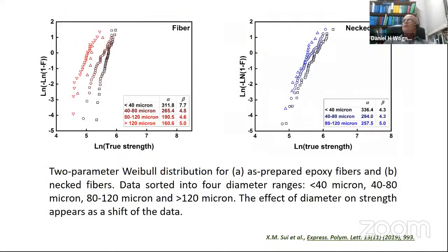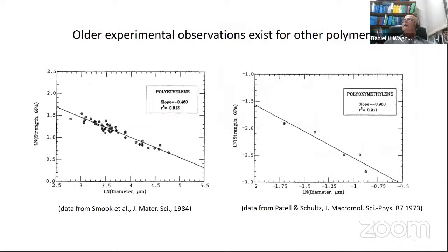The fiber distribution gives you two plots, on the left for as-prepared fibers and on the right for the necked fibers, and the Weibull model fits quite well. It's been sorted in 4 diameter ranges, and the effect of diameter on the strength, as expected, appears as a shift of the data.